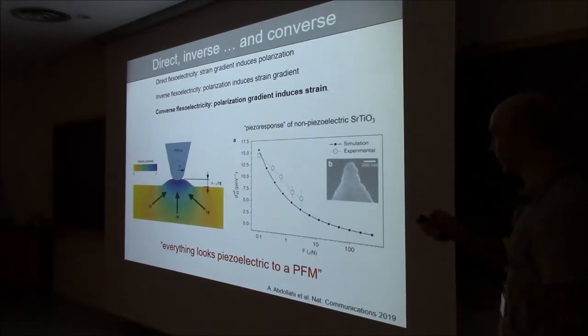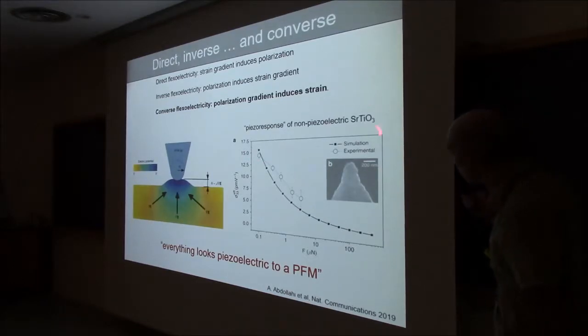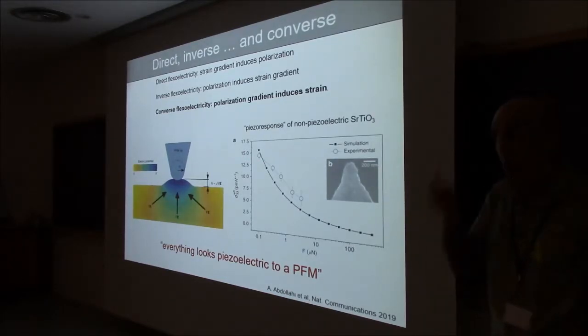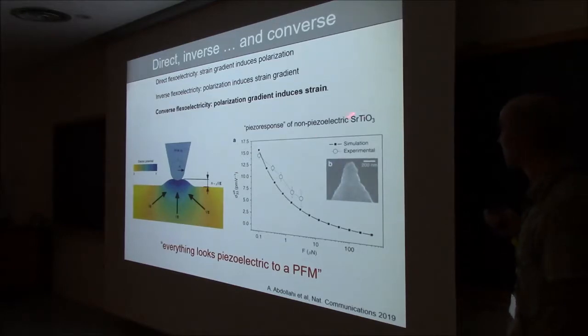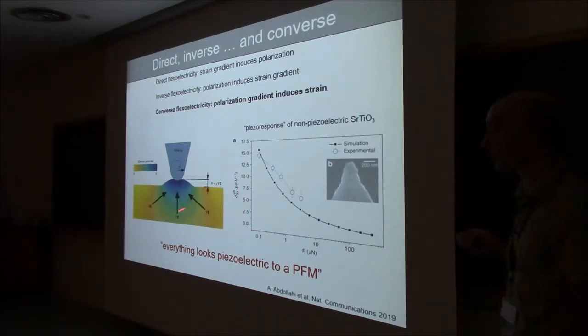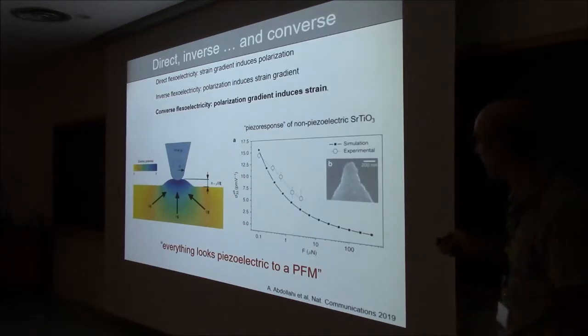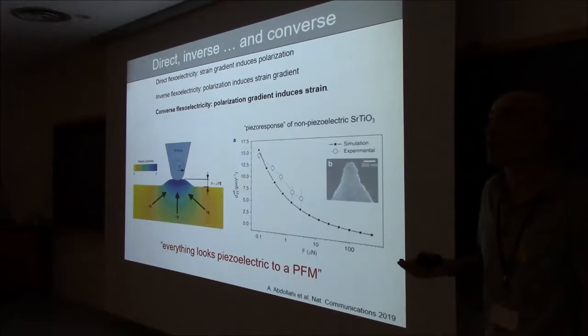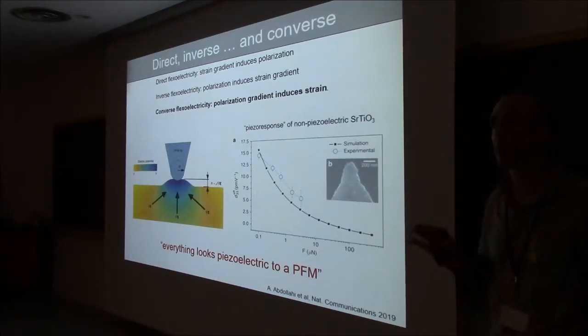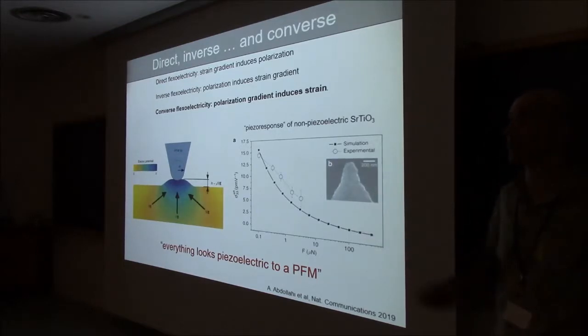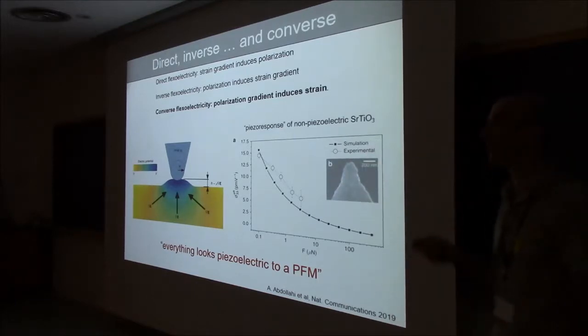Right, so as an example of what I'm just saying, if you look at strontium titanate and you try to measure PFM on the surface of strontium titanate, you will see a very measurable piezoelectric coefficient. I mean, this is sizable, of the order of a few units or tens of picometers per volt, which is bigger than the piezoelectric coefficient of quartz. So I mean, it's not negligible. That's STO. We've also tried this with titanium dioxide, rutile, perfectly centrosymmetric, and you also see a flexoelectric, a piezoelectric-like coefficient that is given by converse flexoelectricity.